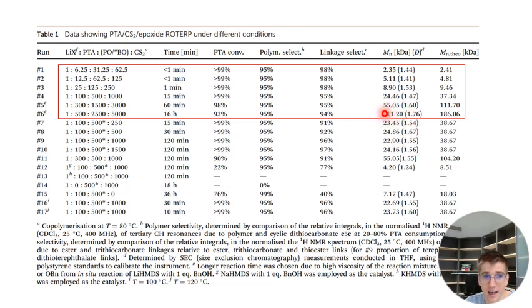This is not always the case. We then showed otherwise for such sequence selective polymerizations that you decrease the loading. If you have some sort of controlled or living polymerization, you'd expect that if one initiator, the alkoxide, enchains more and more monomers by having more monomers per initiator, that you form longer and longer chains, right? That would be the baseline assumption, but this is not always the case in reality due to side reactions other than the ones that I showed you. But the dispersities, even for these types of polymers, were not the worst, but somewhat broad. And we didn't investigate in this study why this was the case. But it is something to point out.